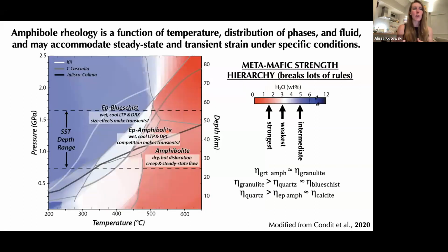Based on the macroscopic strength contrast from other rocks and minerals, we can construct a metamafic strength hierarchy. This I find really interesting because it actually breaks a lot of conventional rules of how we think about material strength. That's because the hot rocks, the amphibolites, are actually the strongest, exhibiting similar strengths to granulite and pyroxenite. And the wettest rocks, the blueschists, are not the weakest. So we actually have this sort of jump across the metamorphic diagram in terms of strongest, weakest, and somewhere in the middle. And interestingly, we see all these different rocks with all these different mechanisms across this zone where deep slow slip and tremor occurs. So there's very different aspects related to the rock strength here and deformation mechanisms, which may feed into creating these slow slip phenomena.